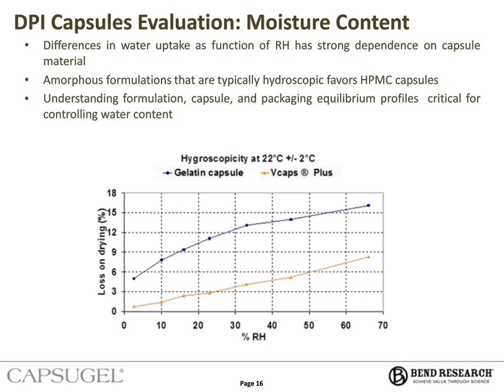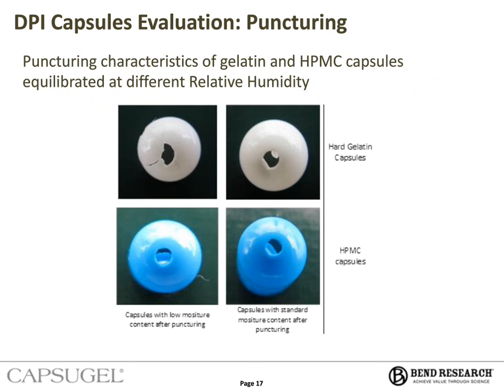In relation with the moisture content, you have to keep in mind that this water bound to the polymer may have an impact on the mechanical properties of the polymer. And we'll see that on this slide, you have photos of capsule after puncturing. So the white capsules are gelatin capsules, and the blue capsules are HPMC capsules. On the right-hand side, the capsules are what we call standard. The moisture is equilibrated to 50% relative humidity. And you can see that the hole obtained after puncture is very nice, and there is no particle detached.